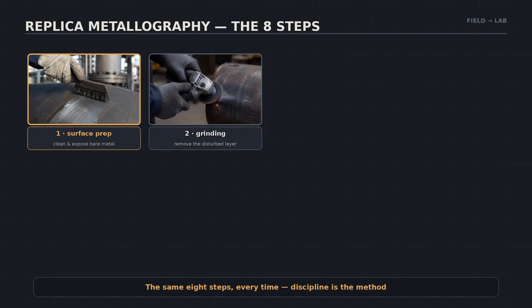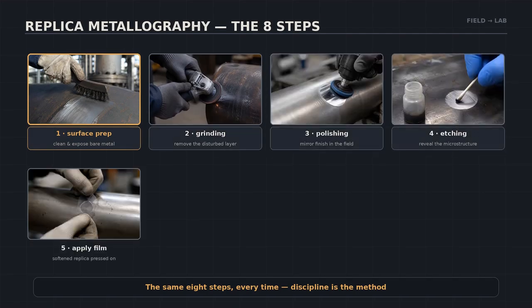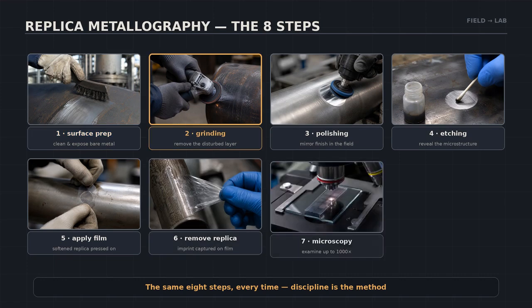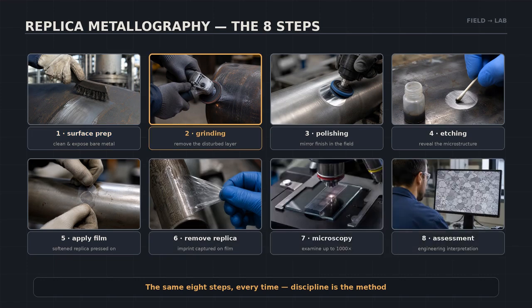The method is 8 disciplined steps. First, surface preparation, clean down to bare metal. Then grinding, to remove the mechanically disturbed layer. Then polishing, and yes, you can get a mirror finish in the field. Etching comes next, a few seconds of chemical attack reveals the grain structure underneath.